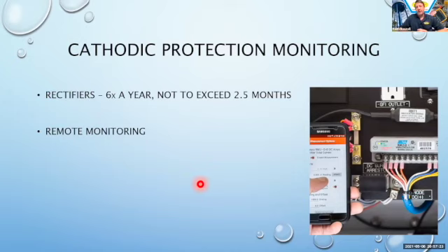Monitoring of the cathodic protection is twofold. The first set of monitoring is to monitor those rectifiers, the power sources to the cathodic protection systems. Those are monitored 6 times a year, not to exceed 2.5 months. The premise there is to make sure there's power to those rectifiers. If there's no power, then we don't have any cathodic protection on those crude pipings. So they're monitored on a regular basis to make sure they're operational and that they're within their set limits of what they want those systems to operate at.